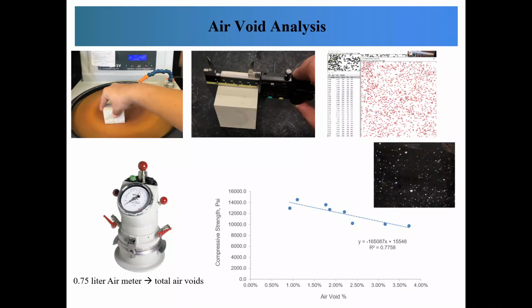Another parameter to pay attention to is the amount of entrapped air. We have used two approaches. First, the mini air meter for total air void content, and second, filling air voids of the ground UHPC surface, followed by digital photo analysis. Then the air voids have been linked to the compressive strength, and a linear correlation between them has been drawn for the mixes investigated in this part of the research. This is important for a representative comparison of the compressive strength of mixes with different air content.